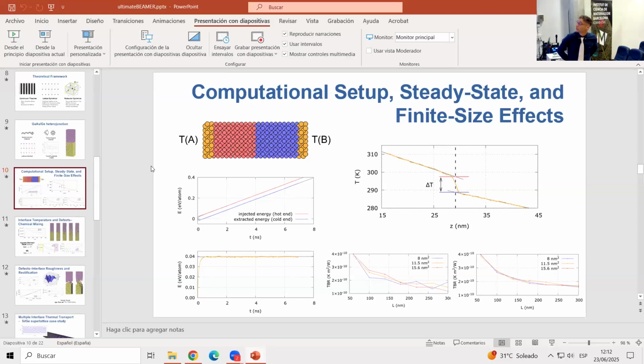And with this method, you don't see any temperature jump in between the thermostat and the system. Here you show the profile within the free atoms. I am sure, yeah, this is just a region close to the interface, of course. You also have a TBR between the thermostat and the system as well? It is not a TBR because, I'm just recollecting my memories, you don't see a sharp drop. You see a smooth, very pronounced drop, but it's a smooth one, and it's completely non-physical.